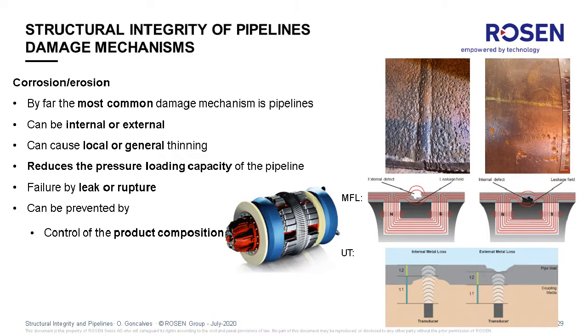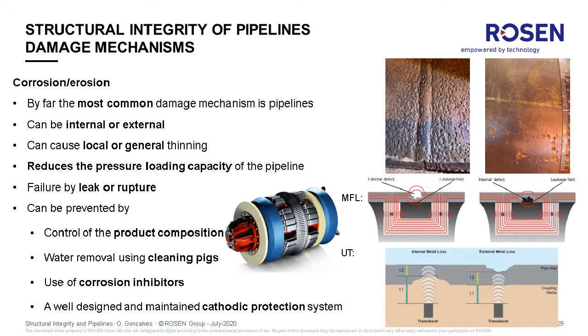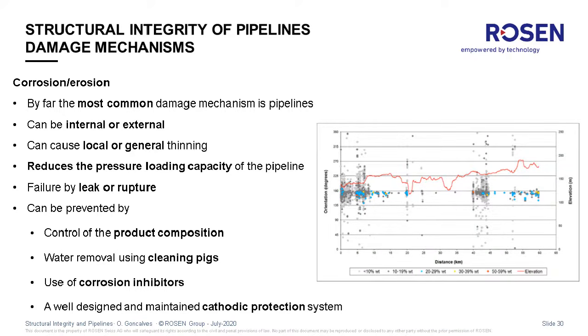It can be prevented by a control in the product composition, water removal, also using cleaning pigs that basically drag the water away from the pipeline. Because water presents a big contribution for internal corrosion, and also the use of corrosion inhibitors can help to avoid internal corrosion. And of course, a well-designed cathodic protection system.